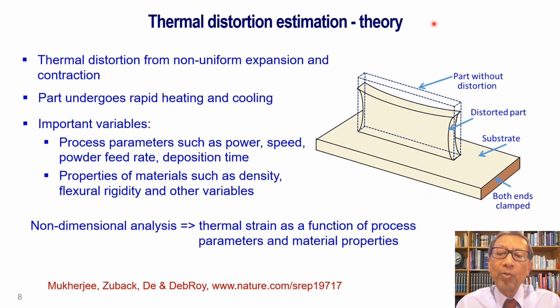Distortion is very common because of rapid heating and cooling, and important variables that affect the distortion include process variables such as power, speed, powder feed rate, and deposition time, and also material properties such as density, rigidity of the material, and other parameters that affect the extent of distortion. So our goal is to express maximum strain as a function of process variables and material properties.